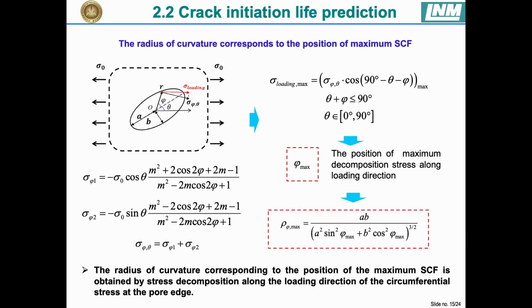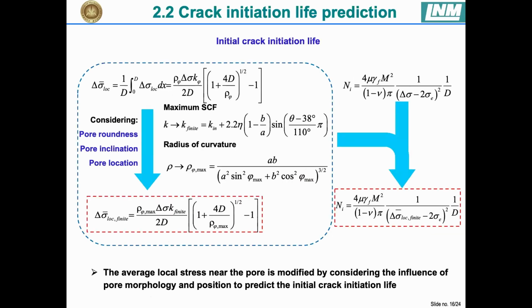Then the radius of curvature corresponding to the position of the maximum stress concentration factor can be obtained by stress decomposition along the loading direction. The position of the maximum decomposed stress along the loading direction is phi-max, and then the corresponding radius of curvature can be obtained. Therefore, the average local stress can be modified by considering the pore roundness, inclination, and location. And then it is substituted into the Chan model to predict the crack initiation life.